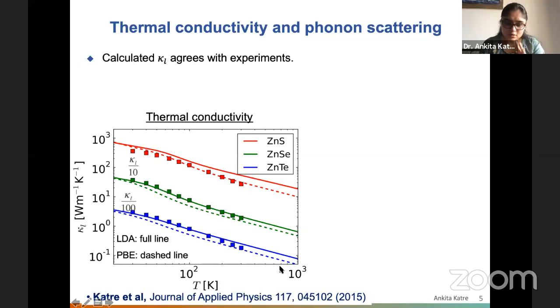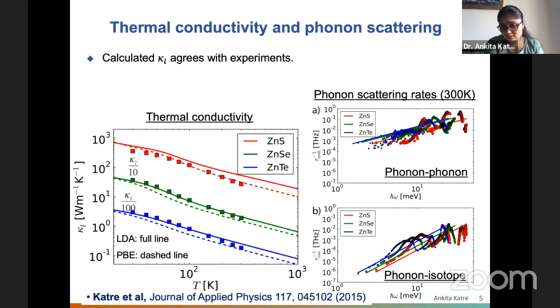So we see that on average we have a good correspondence with the experiments, and over a bigger temperature range as well. So now we know that the thermal conductivity calculations are matching with the experiments. These results are basically with anharmonic as well as isotope scattering. Now let's see how much the effect of isotope scattering is in these materials. These are the phonon scattering rates that I have pulled out. The first plot is phonon-phonon scattering.